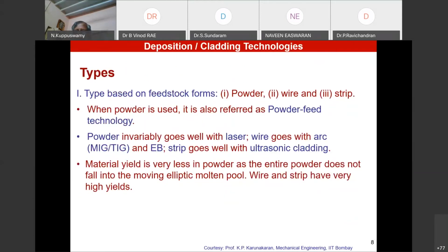Now, when it comes to laser cladding or deposition technology, which is also called laser metal deposition, you have a choice between a powder, wire, and a strip. In this process, the powder utilization is only 40%. Whereas if you use a wire, you are able to go up to 90% utilization, 95 even. So is it for a strip. Now, the disadvantage of wire and strip could be to do with the resolution you are able to get and the layer thickness you are able to build. And in almost both cases, you will have to do machining subsequently.